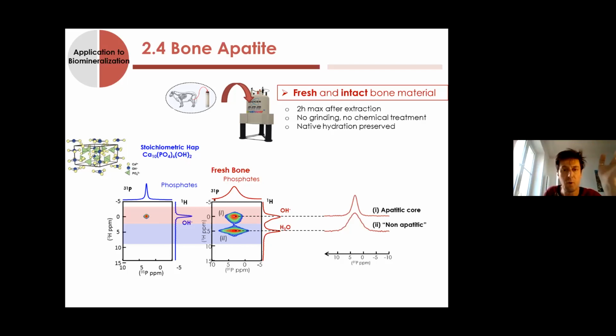That's pretty normal. If you do the same with fresh bone, actually you don't have one resonance, but two resonances. So it means that under the broad peak you saw before, there are actually two different resonances.